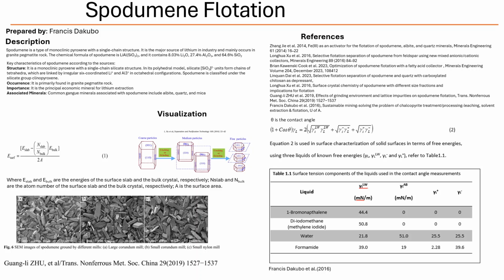Built-in imperfections. Right. And the computational studies, using density functional theory, or DFT, those super detailed atomic models, suggest that iron (Fe) and calcium (Ca) are quite likely to substitute for aluminum atoms within the spodumene lattice. Magnesium (Mg) seems less likely to fit in that way. So naturally occurring iron and calcium inside the crystal structure affect flotation. It seems so, particularly iron.